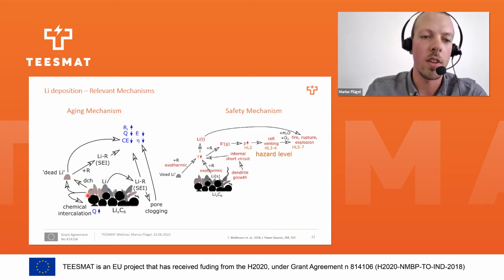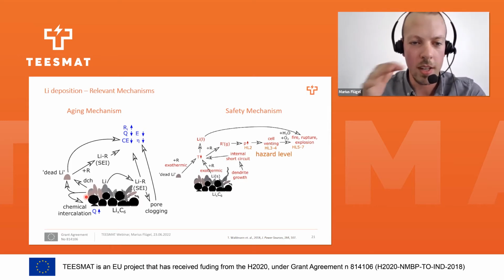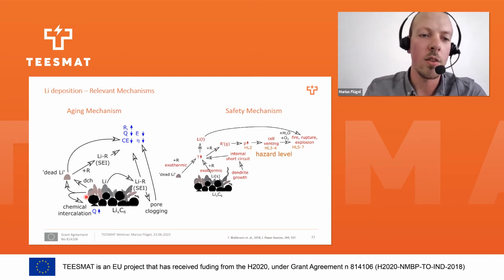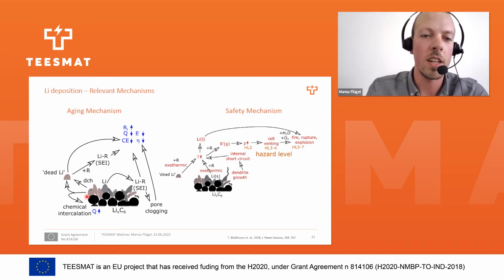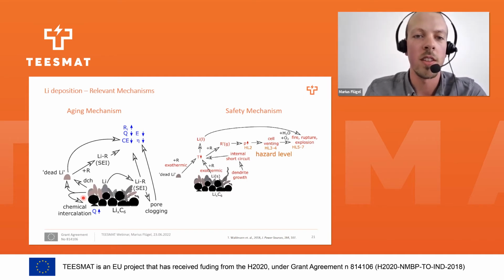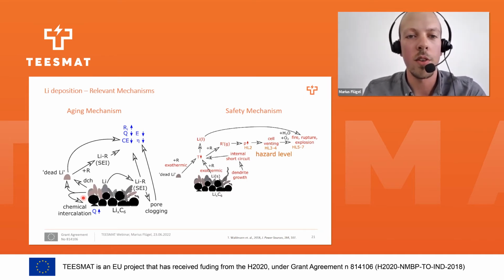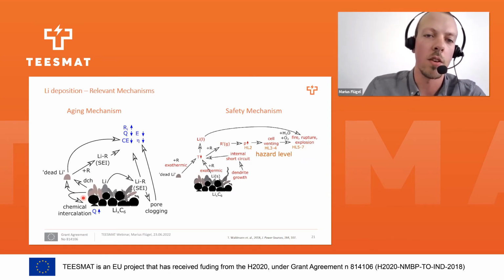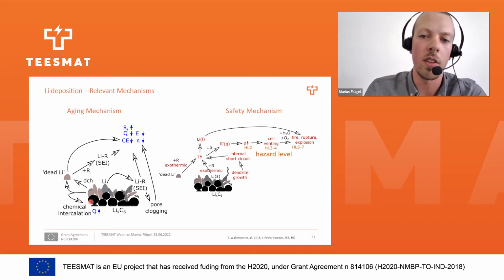However, some of the lithium may not have contact to the anode anymore and is therefore so-called dead lithium, which can react with the electrolyte and form SEI components, which are then blocking the pores. This leads to an increase of the internal resistance and a decrease of the Coulombic efficiency and the capacity of the cell. The energy and the energy efficiency also decrease.